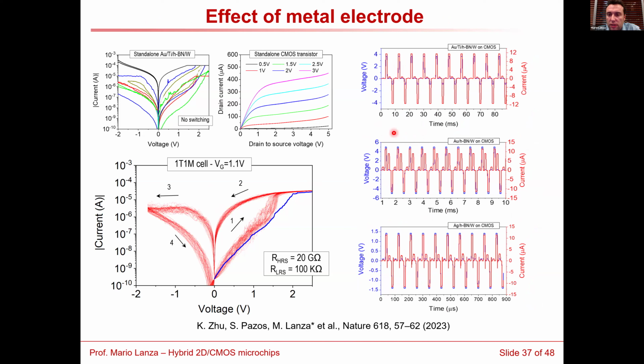And what we observe is that, as you can see, if you see only the reads before and after the write and the erase events, we can see clearly high resistance, low resistance, high resistance, low resistance. So basically, this is confirming the non-volatile bipolar resistive switching by applying pulses.